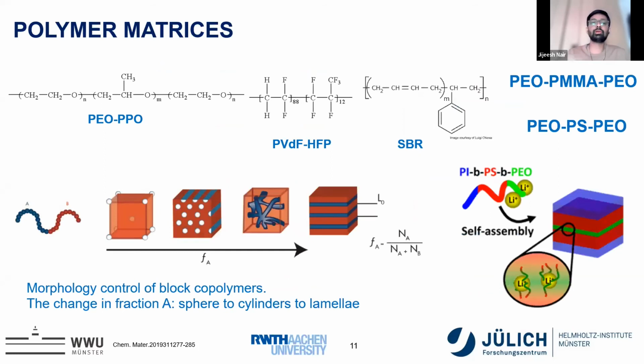What are the advantages you can get, for example, for block copolymers? You can see examples such as PEO, PPO, or PVDF-HFP, or PEO-PMMA. You can really tune, for example, if you look at the bottom left-hand side, a block copolymer which has a part A and part B. By changing the chemistry of part A or part B, or by changing its length, its processing conditions, or its molecular weight of A and B, you can get different kinds of morphologies in the polymer matrix, or different kinds of phase separations in the system, whether it is spherical, cylindrical, or a layered structure. As you can see on the right-hand side, where you have polyisoprene, polystyrene, and PEO.